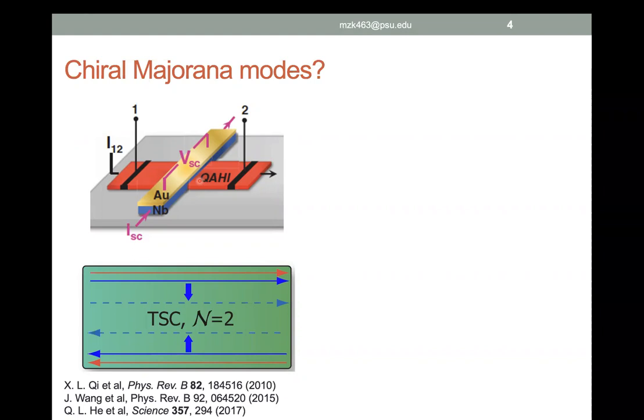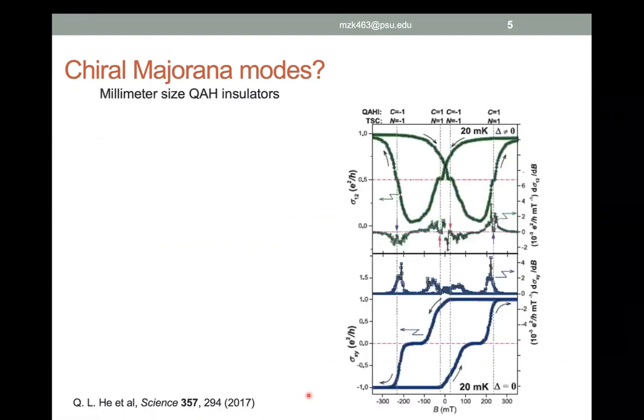The idea here was that during the magnetization reversal of a quantum anomalous insulator, these Majorana modes, of which you have two on each edge, will split, and then eventually you may end up with only one chiral Majorana mode at each edge of this quantum anomalous insulator-superconductor hybrid system. In 2017, a group from UCLA reported the observation of these Majorana modes. The sample they had was a magnetically doped topological insulator. This was a millimeter size sample, with a millimeter size niobium deposited on top of it.